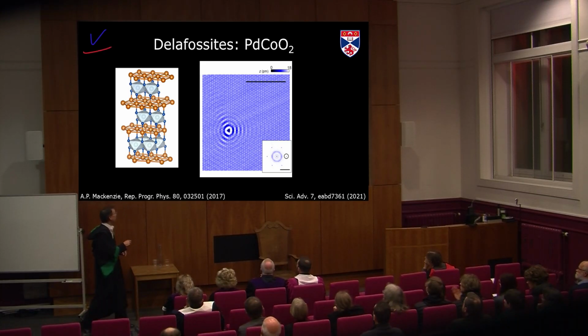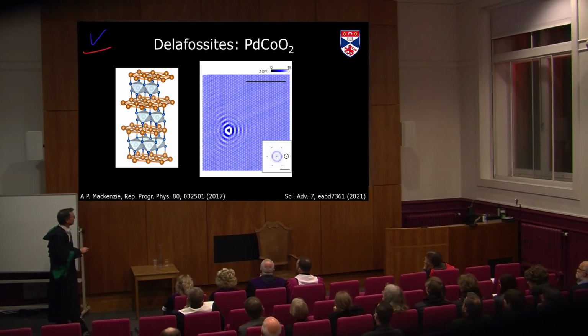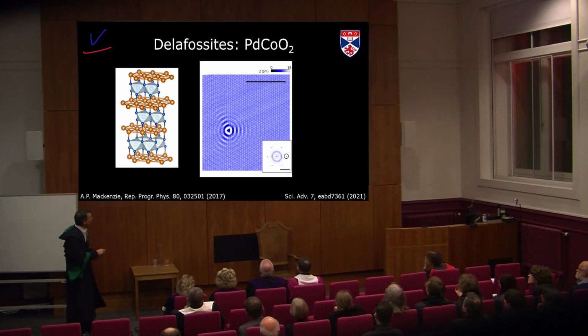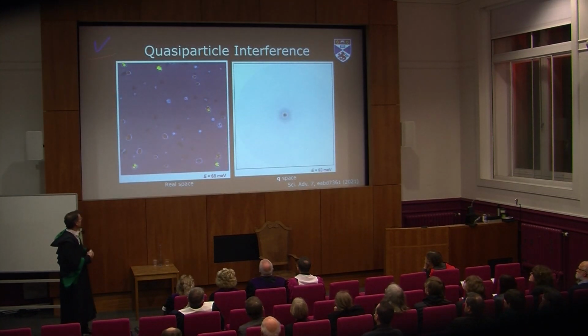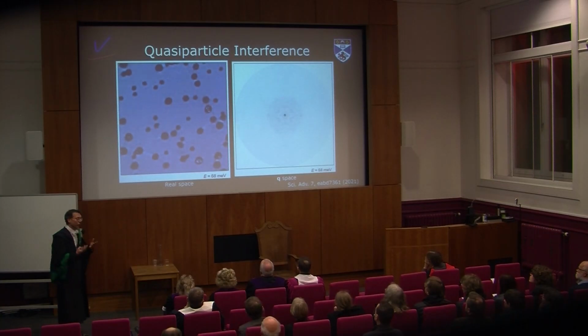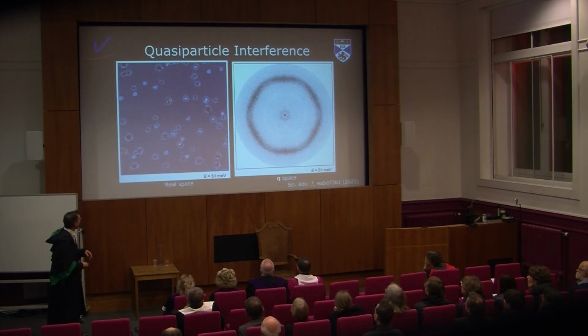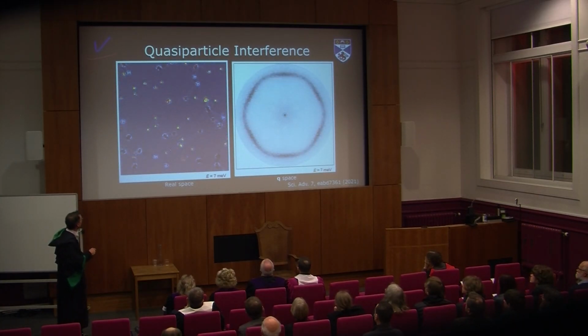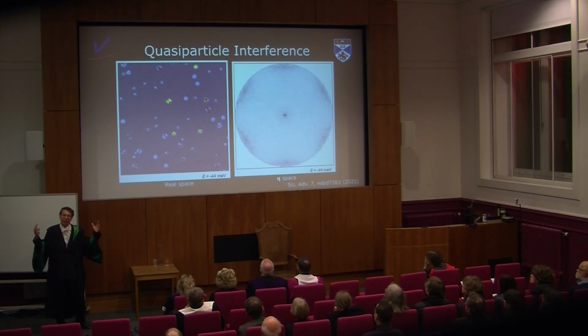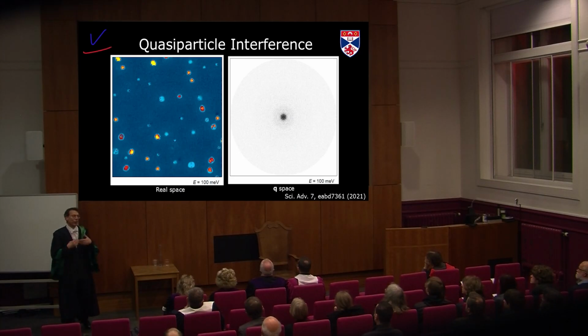You saw this image before with a hexagonal pattern, and this is the Fourier transformation, which shows a nice ring here from these electron ripples, and then these points from the crystal lattice here. And so here's a video of how this looks like now if we record one of these spectroscopic maps, where we can see these ripples as a function of the applied voltage, and you can see how they change their periodicity, how they change their wavelengths. And that's what we call the dispersion of the electrons. That's how we can image the electronic structure.